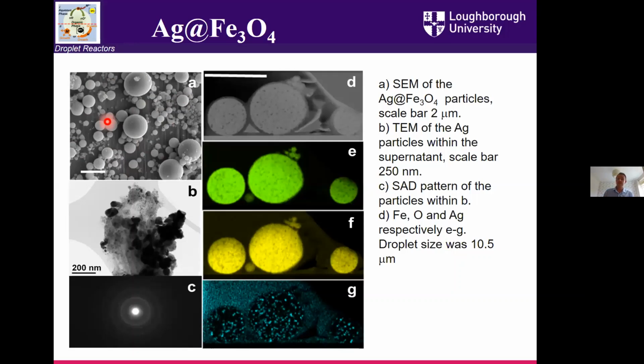And so when you see something like this on your SEM, it shows you that those emulsion droplets weren't stable. During that reaction process, something's happened to destabilize it. You've got them coalescing, dropping out. I've got a wide range of sizes here. And not only were we getting magnetic particles from a process when we had silver and iron oxide, but we were getting a lot of nanomaterials within the liquid, which were silver. And so this is the diffraction pattern of those nanomaterials. And the elemental analysis tells us that they're silver. So we're making silver particles, but they're not staying with the droplet. Yeah, they're being shed into solution afterwards.